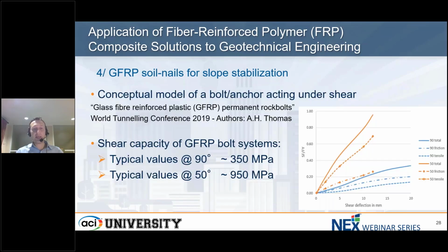To explain a bit about that, I invite you to study a very interesting paper from Dr. Thomas, who published it at the World Tunneling Conference. I won't have the time to explain all in detail here, but the reason GFRP can have such behavior is because of the tensile properties. When you get this deformation, some of the stress will be taken in the tensile properties, and some will be in the frictional. And GFRP being so strong in tensile, you really get this contribution when you have the system working in shear, and that gives you, with the model developed by Dr. Thomas, 350 MPa at 90 degrees, which is what we observed. What's interesting is if you were to do that at a different angle, like we often see in geotechnical work, GFRP would exceed the performance of steel, and that allows us even to get better behavior.